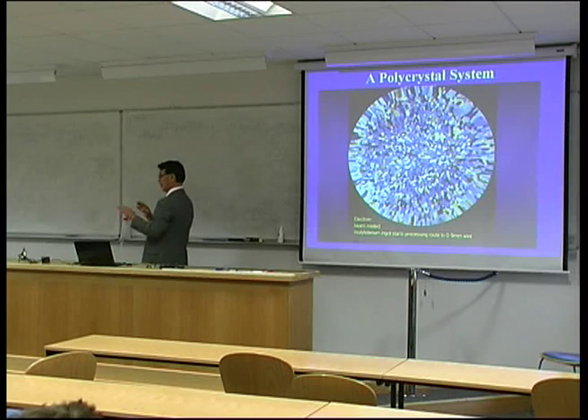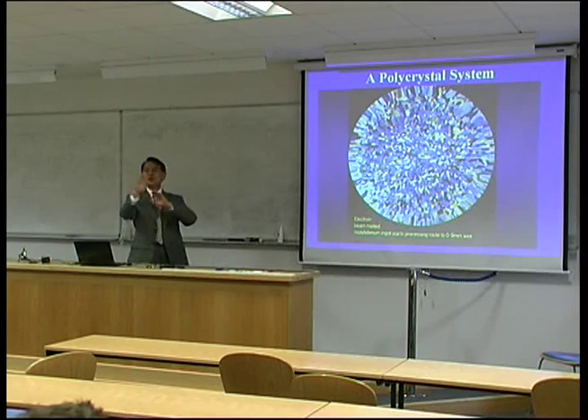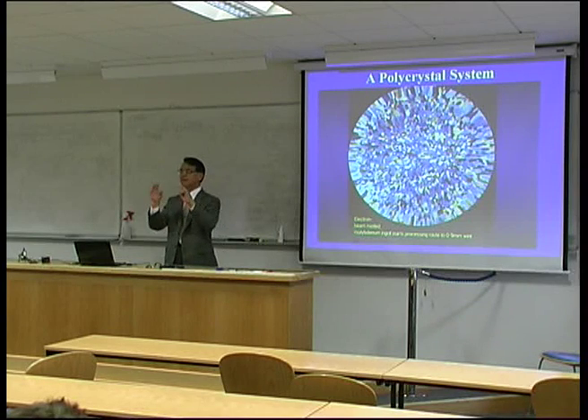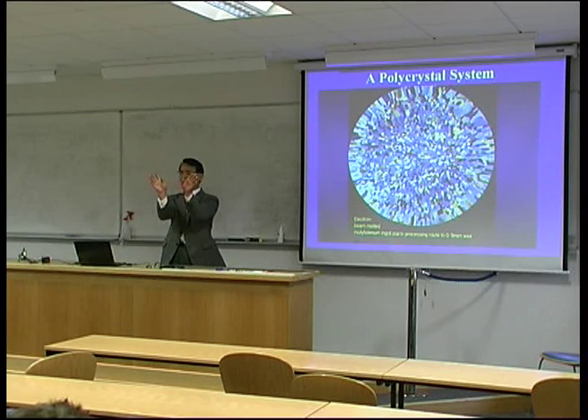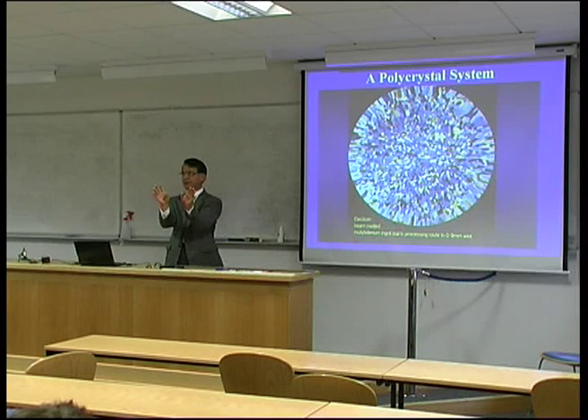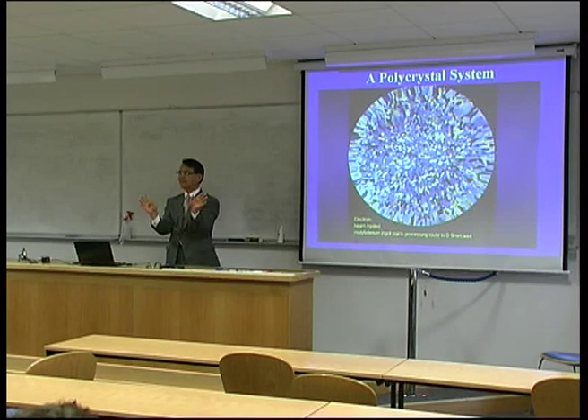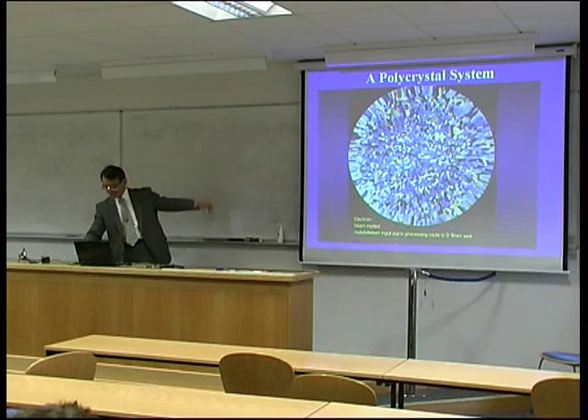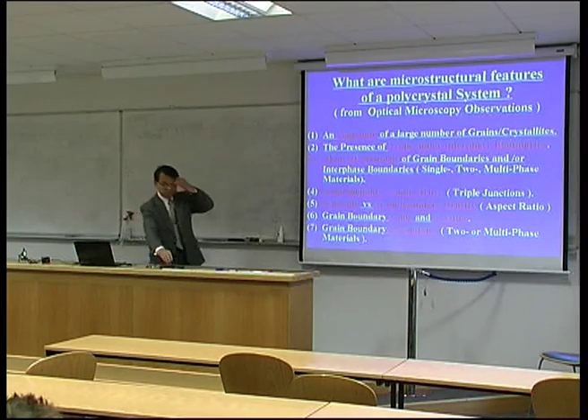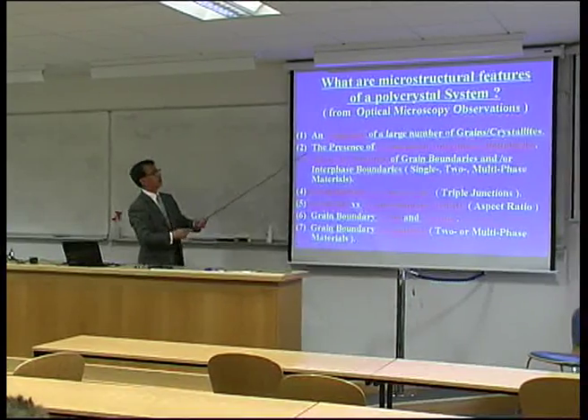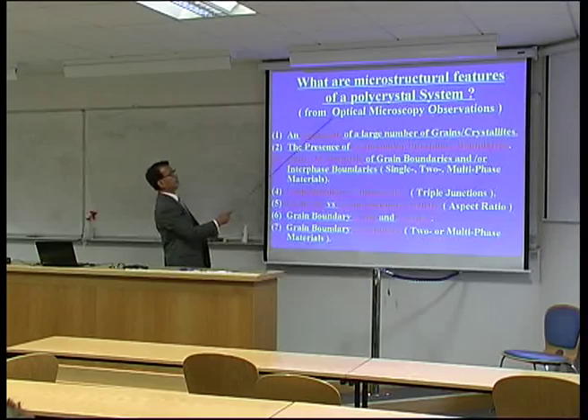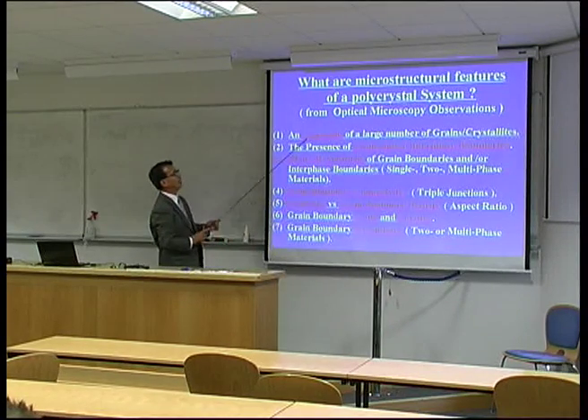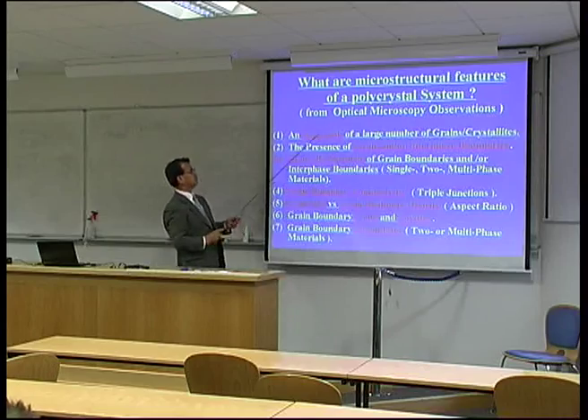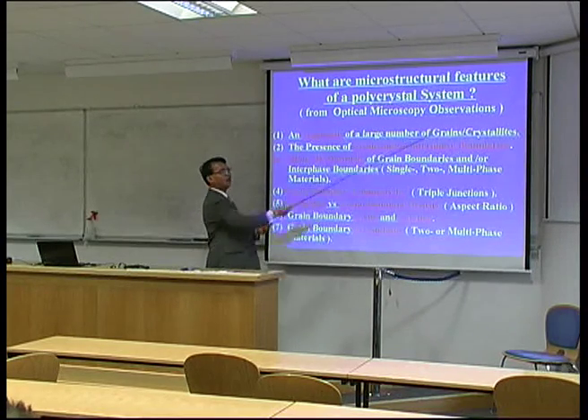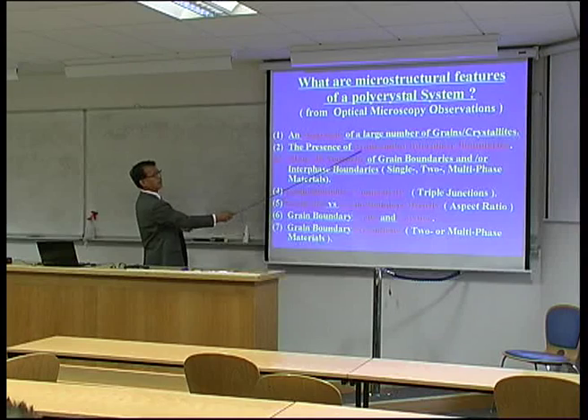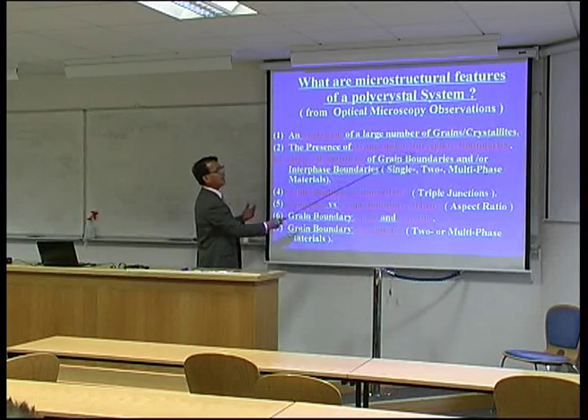So I'm going to mention later, we have to classify the type or character of a boundary depending on the relative orientation, the misorientation relationship, for a smaller angle boundary or higher angle boundary. But anyway, this is the reality in polycrystal material. Even at the level of optical microscope observation, the polycrystalline system is an aggregate of a large number of grains or crystallites, and between one grain and another grain, we can recognize a grain boundary or interface.